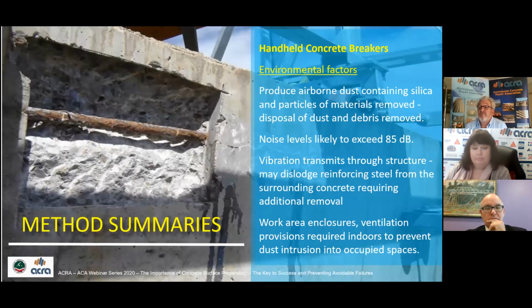Environmental factors, concrete breakers will produce airborne dust. So we've got the containment of dust, and we've got to dispose of the dust and the debris. Noise levels exceed 85 decibels. Vibration levels are moderate to severe. Vibration can transmit through the structure, and the vibration of the reinforcing steel may dislodge the reinforcing steel from the surrounding concrete. So yes, we need to be wary of that.